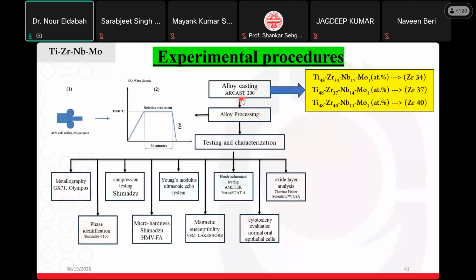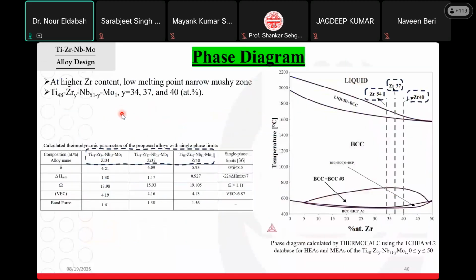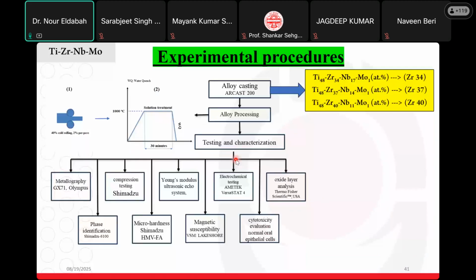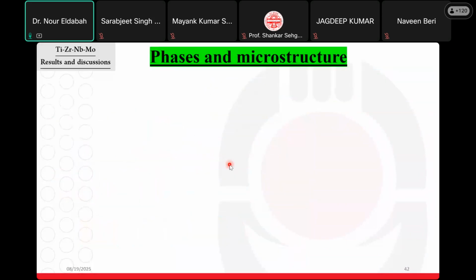Now, in this step, you obey the instructions that come from the classical rule and the machine learning, which state that you should stabilize the BCC beta phase. We made a 40% cold rolling deformation for the alloy, and we accomplished a solution treatment at 1000 degrees Celsius to stabilize our alloy in this region, a single BCC beta phase. So now the machine learning is driving the process itself. Going for the testing and characterization, the design step has been terminated, and now we are characterizing our work. Will it be suitable for orthopedic implantation, or will it go out of our target?